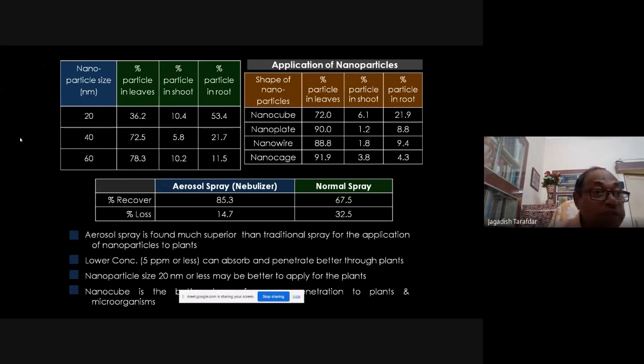With 20 nanometer nanoparticles, after 48 hours, 36.2% we have the spread on leaf, and 53.4% nanoparticle we find in root. That means 53% of nanoparticles within 48 hours penetrated from leaf to root, the entire pathway. But if it is 40 nanometer size, then only 21%. If it is 60 nanometer size, only 11%. So the smaller the nanoparticle, the better their penetration.